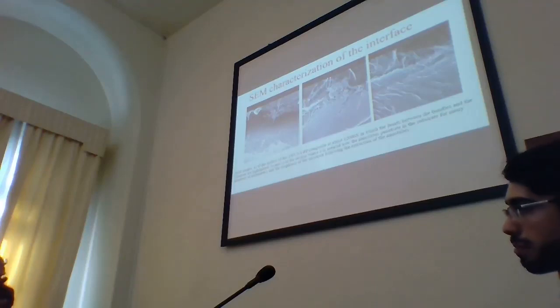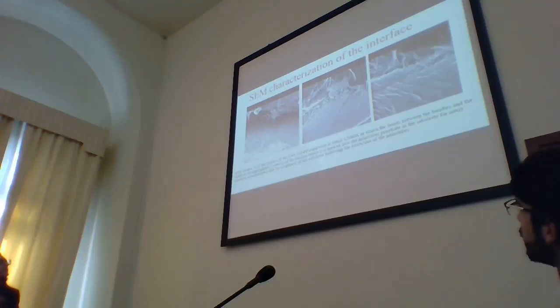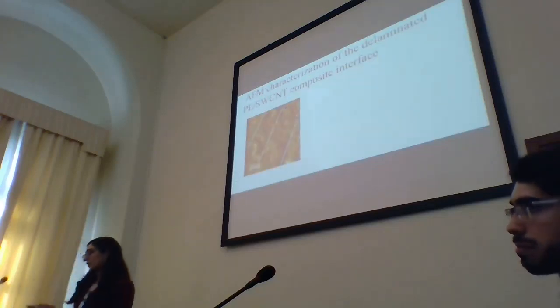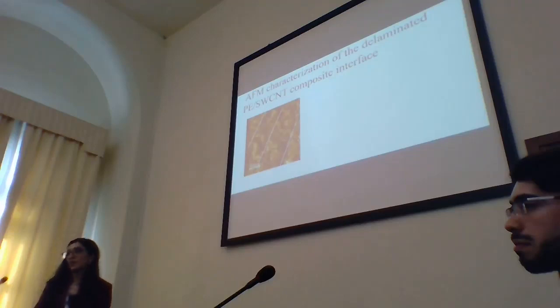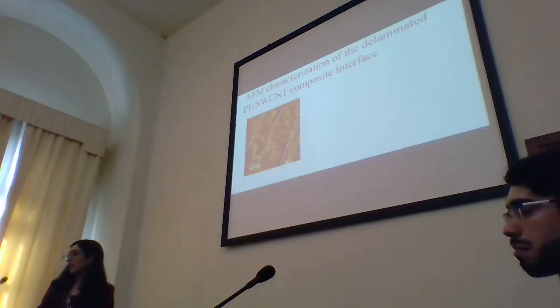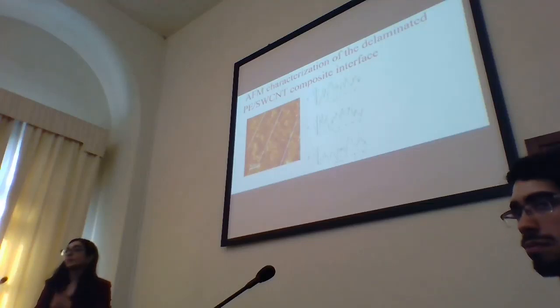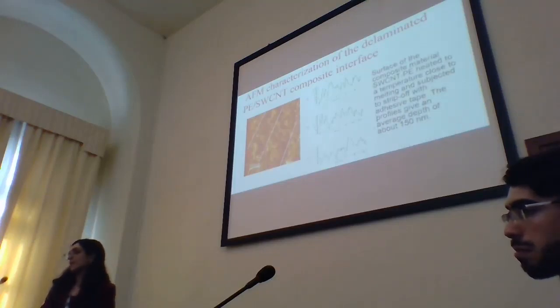These are images of the section of the same sample, and here we can see that the carbon nanotube penetrates into the substrate, and after the strip off, this roughness shows that the penetration of the carbon nanotube is about 2 microns. Also, if the AFM is not the best probe to measure carbon nanotubes, we have carried out this kind of characterization. From the profile of our composite material after the strip off, after we have removed the upper layer of carbon nanotubes, the profile gives an average dip of about 150 nanometers.